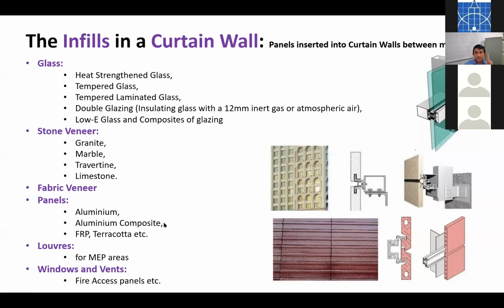If it's high rise, you need to ensure that fire safety is ensured there, because aluminium has a very bad habit of melting away. And although aluminium is non-combustible, the infill in most of the composite panels that you have here is the HDPE, high density polyethylene, which is highly inflammable. It catches flame like nothing on earth. So the regulation in developed countries is either the ceramic infill or to have fire retardant infill within the aluminium composite panel. Then you can have FRP or terracotta, etc.